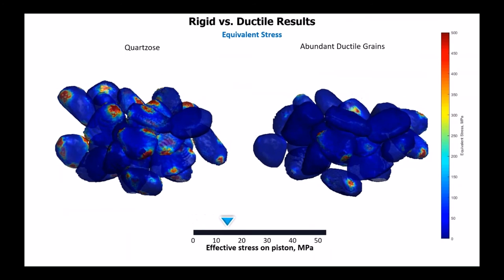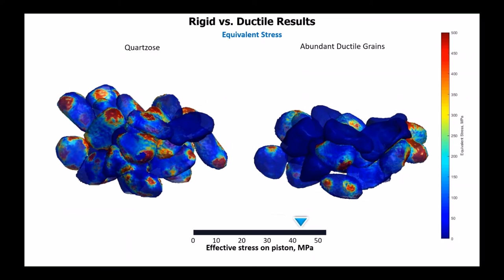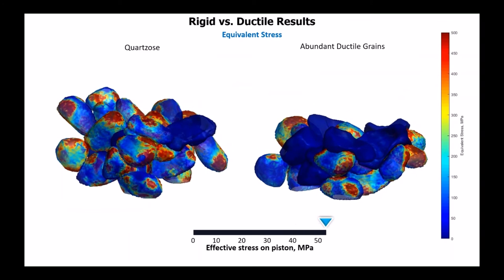And here I'd like to show you some of the grains in the interior of these two packs. What we're looking at is the von Mises equivalent stress on the outer surfaces of these grains. Notice that the shale rock fragments don't show much stress. They're kind of the California surfer dudes of grains. They just go with the flow. They don't get very stressed up, but they deform tremendously. But on the other hand, the quartz grains do get quite stressed.